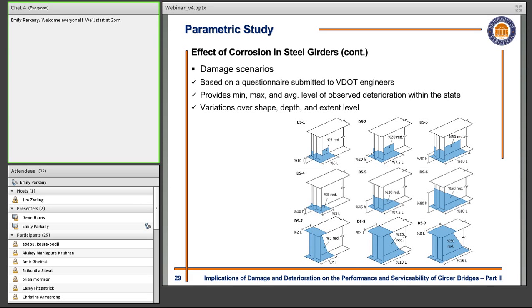So as we got the responses from this questionnaire, we ended up having these 9 representative cases, and we tried to include the variations over shape, depth, and extent level. As you can see in this figure, the first 3 cases represent the damage scenario where we have the rectangular shape of the corroded area. In the second 3 cases, we have triangular shape, and in the last 3 cases, we have trapezoidal shape.